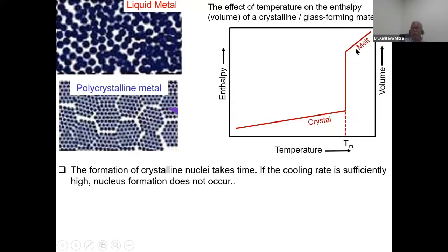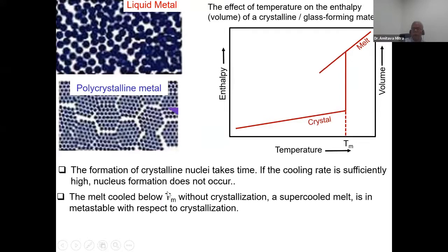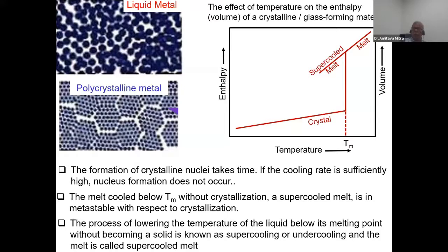But if we now want to cool this material fast, then this crystallization or nucleation for crystallization will not occur. So instead of holding at the melting point, we decrease the temperature first, and this region is called the supercooling of the melt.